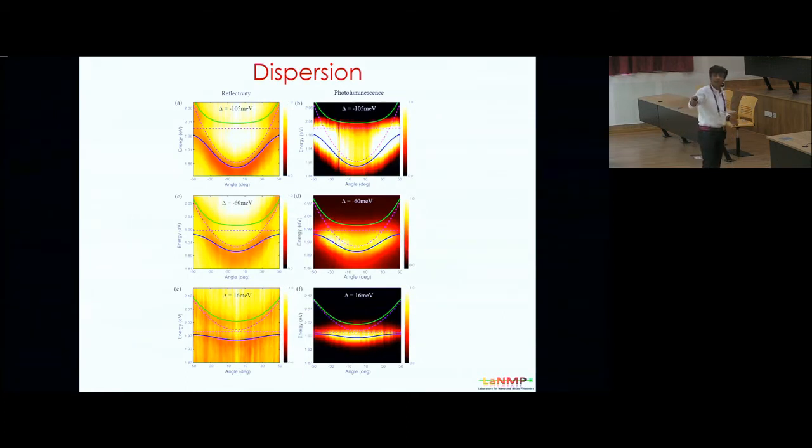You see the typical bottleneck effect on those edges, especially in these large detuned cavities. And at the lowest detuned cavity, actually a positive detuned cavity, most of the emission is coming from the bottom branch. So this is just to prove that even in these really simple metal cavities, we are getting strong coupling in the system. And this is again at room temperature.